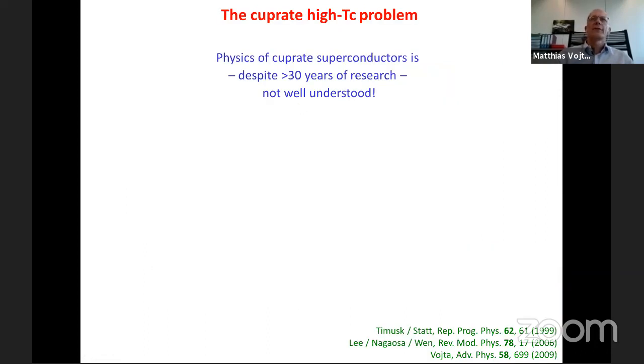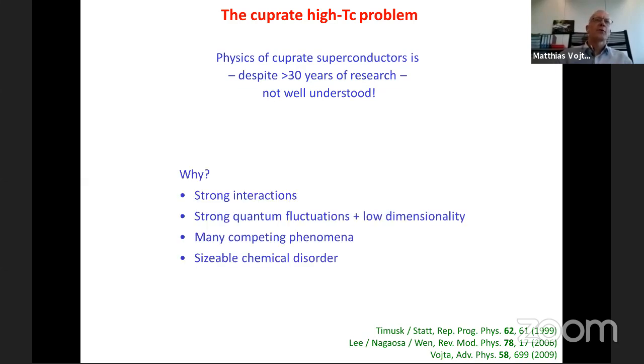And these are the compounds which still, under ambient pressure, have the highest TC. Now, the interesting thing about these materials is that despite more than 30 years of research, their physics is not well understood. This is not because people have not tried, but because it's complicated. The reason is that, first of all, this is a strongly interacting problem, so there are strong quantum fluctuations and low dimensionality. And moreover, it turns out to be complicated because there are many competing phenomena. And it's very difficult to distinguish universal from non-universal properties.